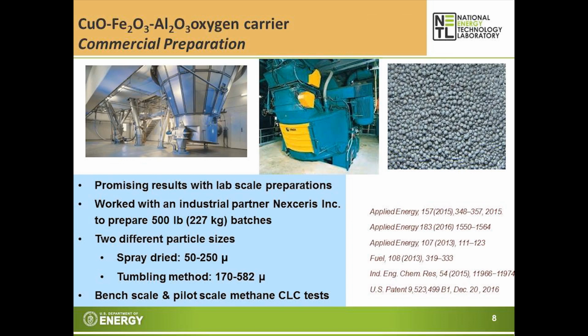So since we saw promising results with our lab scale preparations, we worked with an industrial partner, Nexceris, to prepare 500-pound batches of this material. We added alumina to the copper iron to enhance the strength of the material to get better attrition resistance. We prepared samples with two different particle sizes: spray dried material to get 50 to 250 micron particles, and also the tumbling method, that's pretty much a wet agglomeration method, to produce 170 to 582 micron particle sizes. And then we conducted both bench scale tests and pilot scale methane CLC tests with these materials.